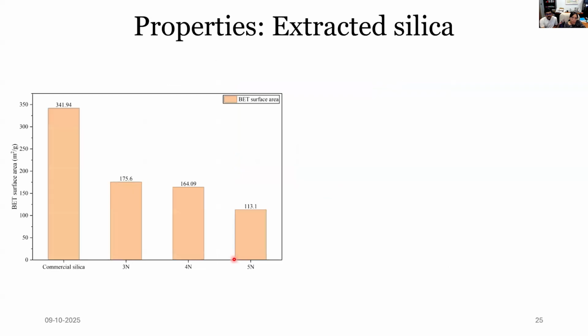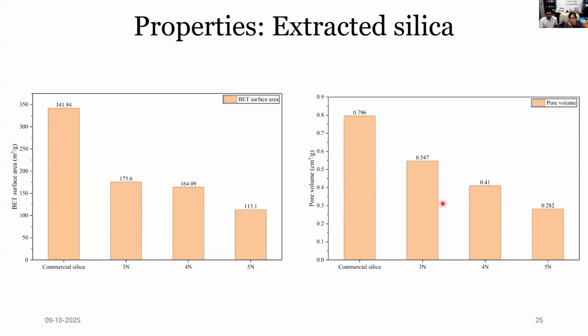And then we also tried to understand some physical properties. In this case, the property we looked at is the specific surface area of the material by the BET method, where the commercial silica had a very high BET surface area of 341.94 meters squared per gram. However, when we increase the sodium hydroxide normality of the synthesized silica, we could see that the surface area starts decreasing. This is mainly because the pore volume in the system starts decreasing when we increase the normality of the sodium hydroxide, which leads to a reduction in the surface area of the system.